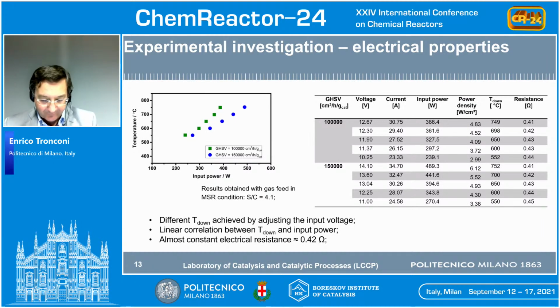The plot shown here on the left shows that we observed essentially a linear correlation between the measured outlet temperature and the corresponding input power. And this is in agreement with the almost constant electrical resistance of the silicon carbide foam across the whole temperature range that we have covered. Moreover, the electrical resistivity that we have estimated from our experiment is around 0.42 ohms, which is in the range of typical values reported for commercial silicon carbide heating elements, which is kind of reassuring for us because it seems to indicate that our experimental setup is working without the presence of additional undesired contact resistances.